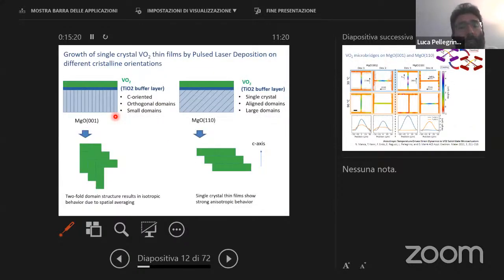Another interesting effect, which is somehow the core of using epitaxial oxides, is mainly due to the fact that we are growing oxides on oxide substrates, so we can completely exploit epitaxial growth properties. We can grow vanadium dioxide and titanium dioxide layers on MgO 001 or MgO 110.